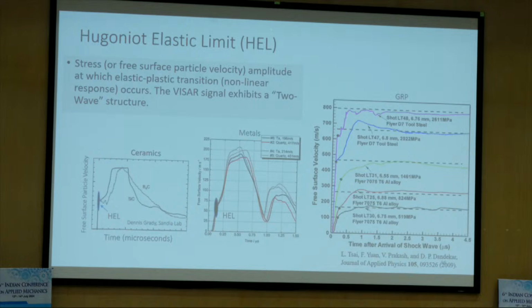This is composite, a mess. I would call it a mess. The data showed, at low velocity, elastic, and then a curve, and then shock stress. You increase the velocity, you again see elastic, and then some dispersion, serious dispersion. You should expect that, right? It has got a weave, it has got fiber, it has got dissimilar materials, it has got impedance mismatch everywhere, and it has got interface.